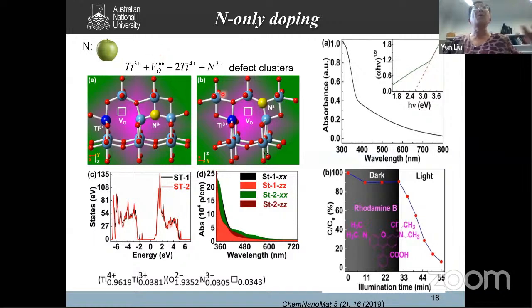So if you have a nitrogen around, you not only generate the oxygen vacancy, but also reduce the nearby titanium-3. These two cases are where the nitrogen is in different locations in the titanium dioxide. Either case slightly improved light absorption and slightly increased the absorption in the visible light range, but not much. The reason is that this kind of oxygen vacancy and titanium-3 does not provide the ideal environment to attract more nitrogen, so the nitrogen contribution level is very low. We tried different ways, and actually you can only go to 3% of nitrogen introduced in this case.